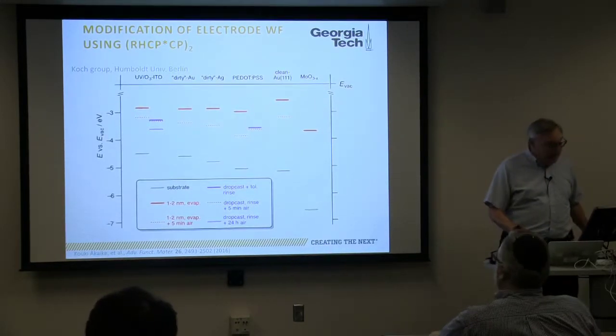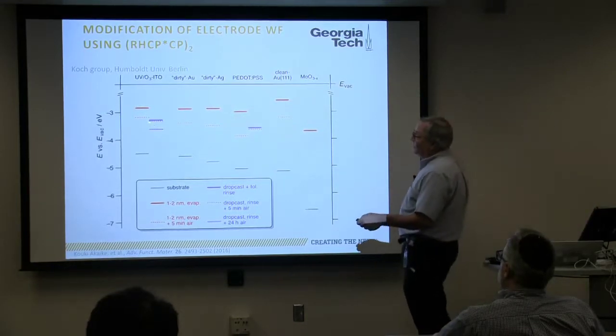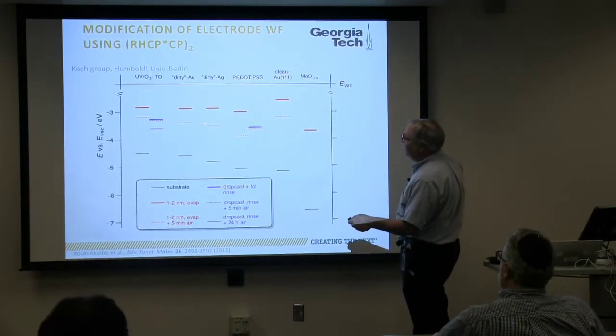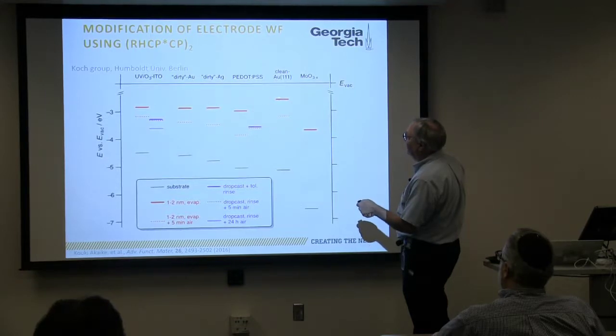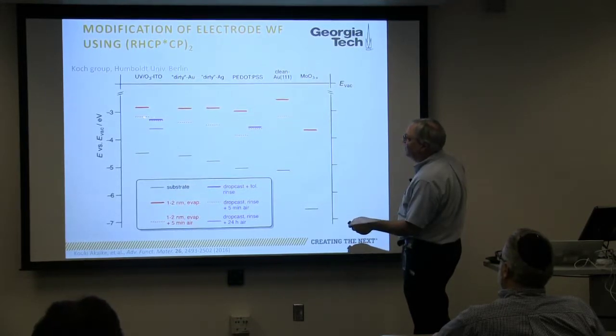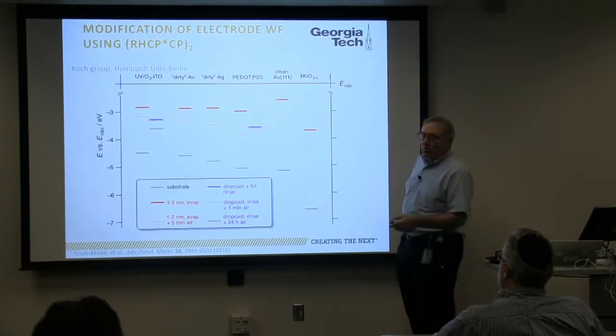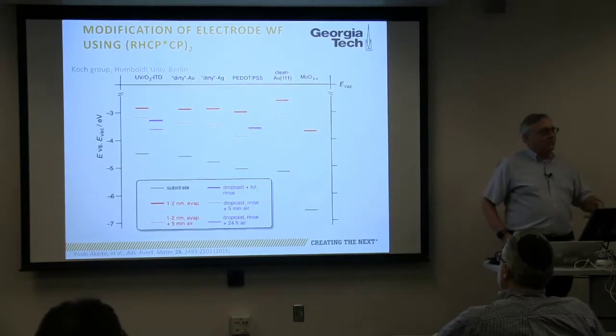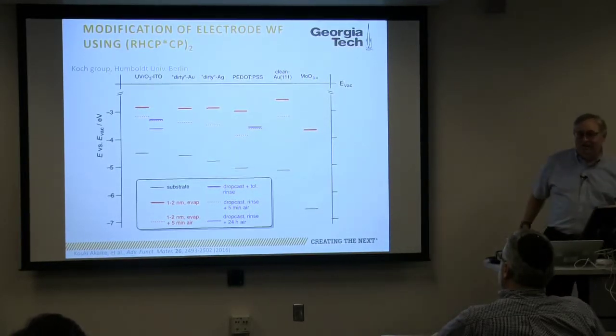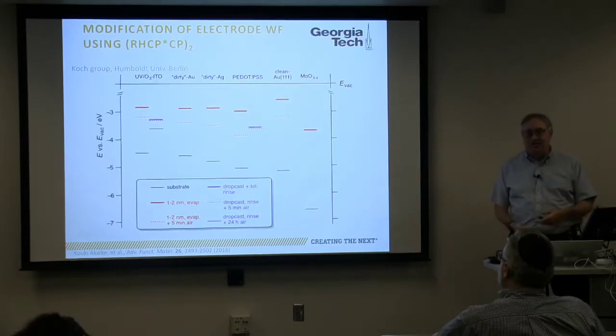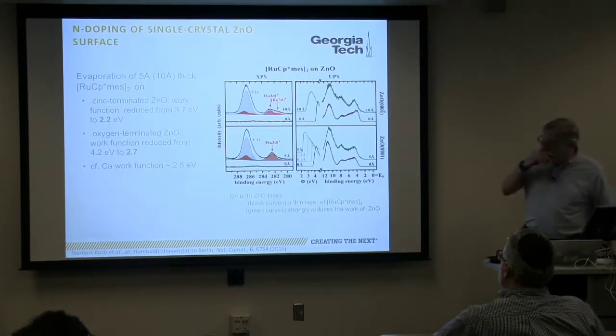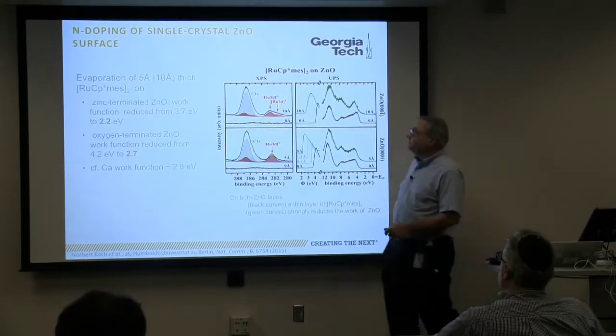And then you expose them to air. And you can see that there is some loss of that decrease in work function, but it stays pretty constant. And the point being that we can make low work function materials that are by and large air stable without having to use things like calcium. A very extreme example of that is shown here.